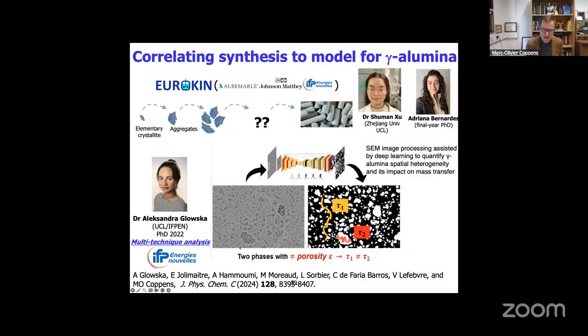And indeed, we looked at images of these materials, and they are very heterogeneous also at a macroscopic scale. So these aluminas, if you have cross-cutting sections here, you see a matrix with some particles inside this matrix, and they may have different local tortuosities. We measured this also using pulsed-field gradient NMR and constructed models to compare this. And so in order to characterize these materials, we really need multiple techniques: adsorption, desorption, even cryoporometry, imaging techniques, mercury porosimetry, X-ray scattering.